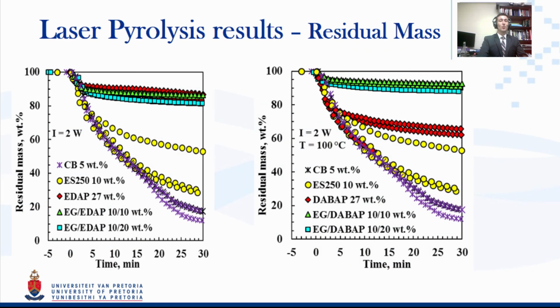Now I'll move on to our laser pyrolysis. One of the things that we found of key interest with the laser pyrolysis is whether our curves will mirror those that we achieve in terms of mass loss from cone calorimetry. So here you can see that for the ES250, the low temperature expandable graphite, in terms of residual mass, it showed some really good results.